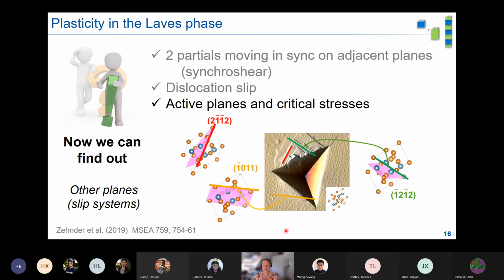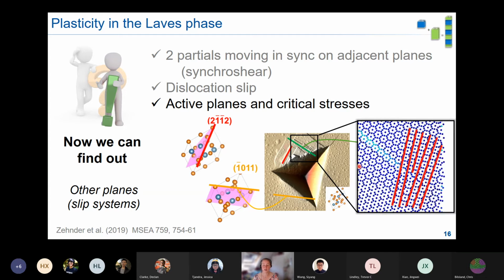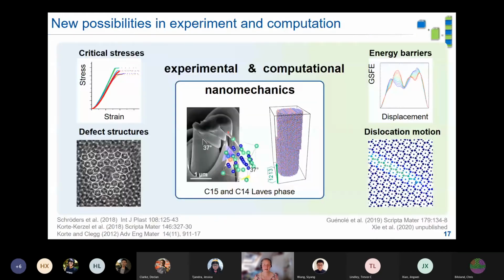Right. Once we have this, we can do quantitative analysis on individual slip systems. We need to get faster. And one of the things we are doing to see which slip systems are actually active, even though we have some candidates maybe, is we use indentation coupled with EBSD so that we can then look at slip traces at the surface. They're not unique solutions, but at least they give us some statistics and guide us where to do micropillar compression or in which to actually look at atomistic simulations, for example, in non-basal mechanisms. So for us, that's actually been quite nice the last few years.